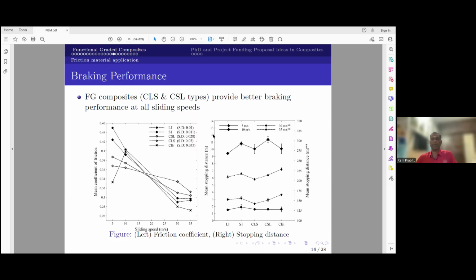Now next is the braking performance. Am I able to stop my aircraft in the distance I desire? Second is, what is the consistency of the coefficient of friction, like my braking performance over the number of landings. Again, both CSL and CLS perform very well, out of which CLS, that is this one, has a very consistent behavior with respect to the increasing sliding speed. Even if my energy changes, my consistency is relatively better compared to other composites, especially the conventionally used. And the stopping distance is also much lower for this composite. So this shows that the CLS composite is superior in braking performance compared to all other composites we have taken for our study.